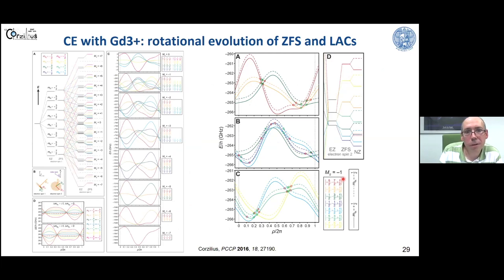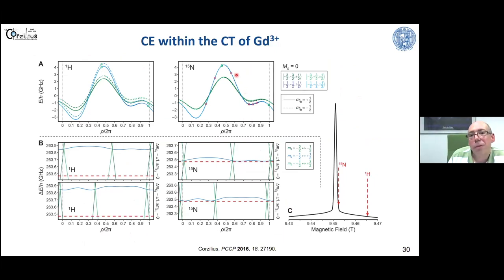And this is just a show-off slide. If you are interested in how cross effect works, I will not talk about these details today, because this would clearly put us way over time. But the zero-field splitting, due to the strong angular dependence, leads to a similar situation as in the g-anisotropy broadened nitroxides. This results in the level anti-crossings that are required for cross effect under MAS, the same way as in nitroxides, by utilizing the different orientations of the g tensors in the pair. This seems to work pretty well for low-gamma nuclei, because then we can match two complexes with each other by working only on the central transitions, even though they are rather narrow.